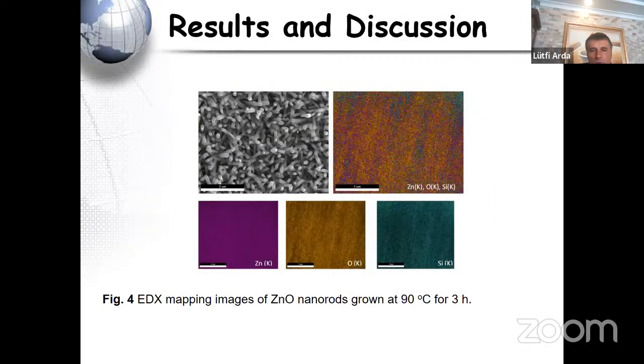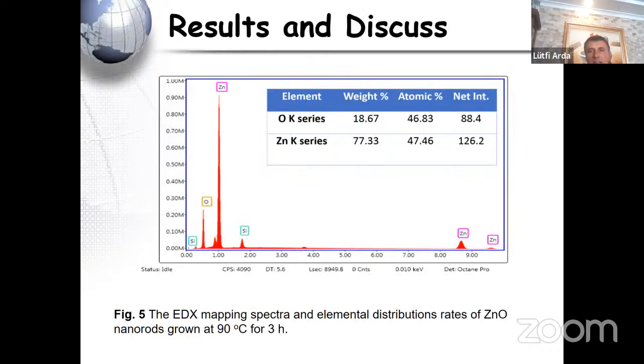Let's move above. The purple, yellow, and green phases correspond to zinc, oxygen, and silicon, respectively. According to the mapping result, the sample contains only two elements, zinc and oxygen, confirming that no elemental impurity is observed. The silicon peak appearing in the spectrum comes from the glass substrate. Also, it can be said that the elemental distribution is quite homogeneous in the zinc oxide nanorod arrays, according to the data given in the next slide.